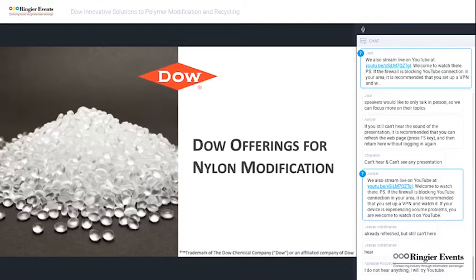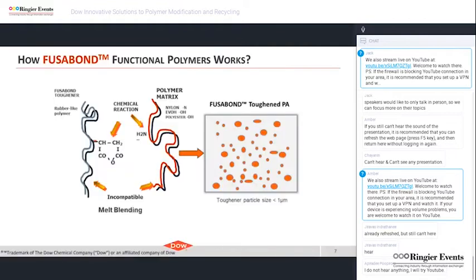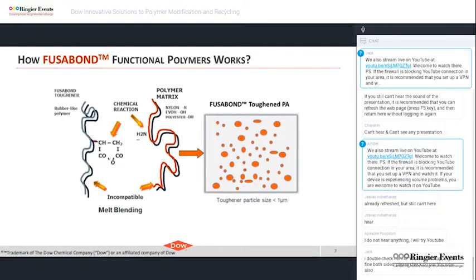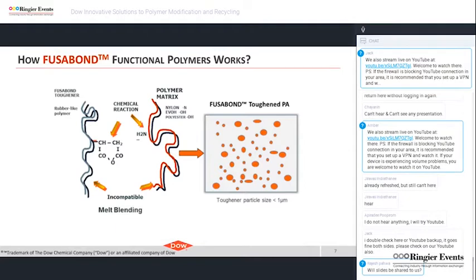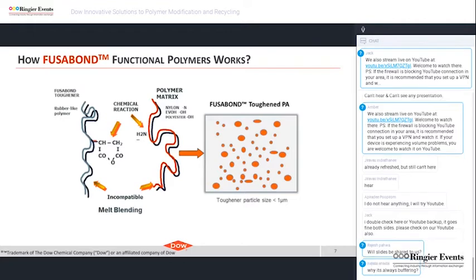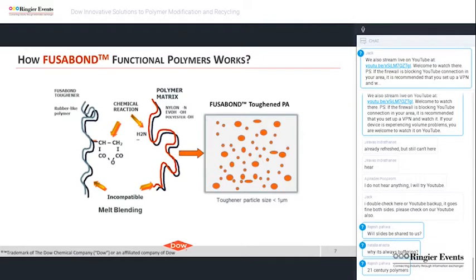Moving on to Dow offerings for nylon modification. Fusabond is a functional polymer having anhydride functionality. Without maleic anhydride functionality, polyolefin is not compatible with polyamide. Maleic anhydride functionality can react with amine functional group in polyamide and compatibilize the blend. After melt blending Fusabond and polyamide, Fusabond particle size could be typically 200 to 300 nanometer.